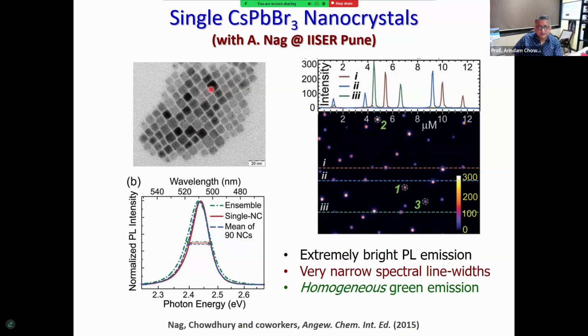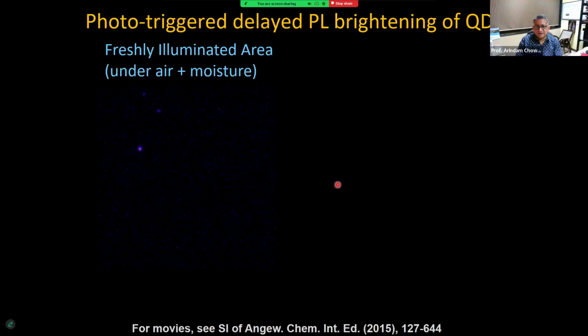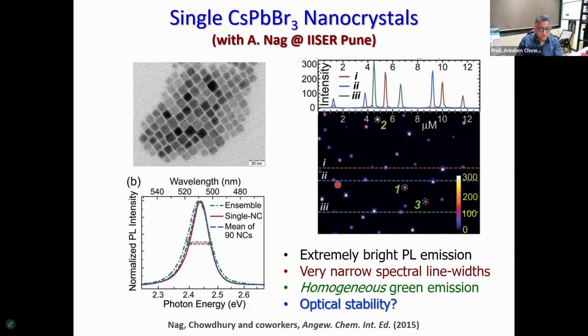We looked at these 11 nanometer size nanocrystals, and we found out they were extremely bright. They had very, very narrow spectra. But more interestingly, once we put them in the microscope and we looked at it, this is what we found out. Again, I'm going to show it again to you.